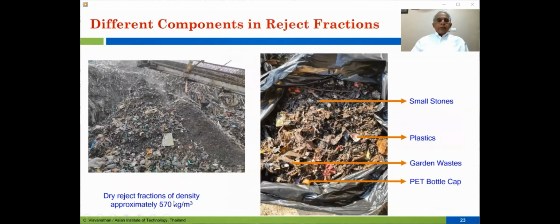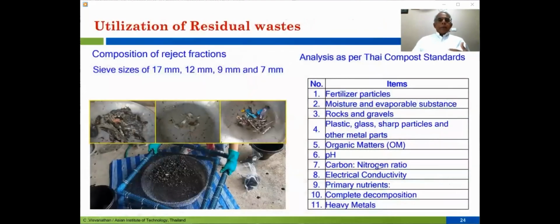Dry reject fractions have a density of around 570 kilograms per cubic meter, and consist of stones, plastic, garden waste, PET bottles, etc. Now, one of the issues is what do you do with this? You need to look at it. So what we did is a composition analysis. We took the reject and did a sieve analysis using different sieves of 17 millimeters, 12 millimeters, 9 and 7 millimeters, and looked at the sieved fractions in terms of fertilizers, moisture content, gravels, etc. Different parameters we looked at.